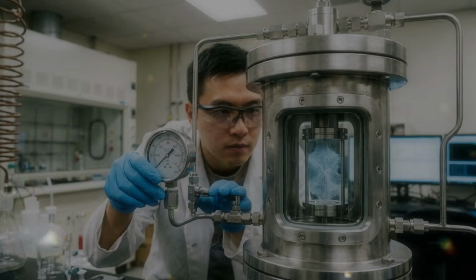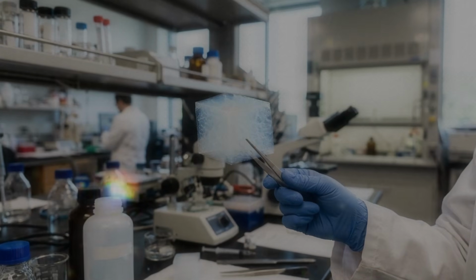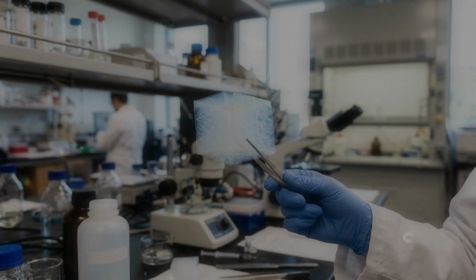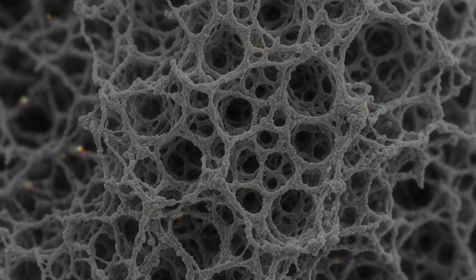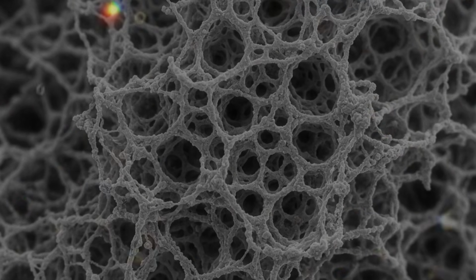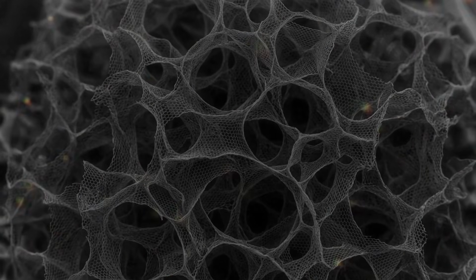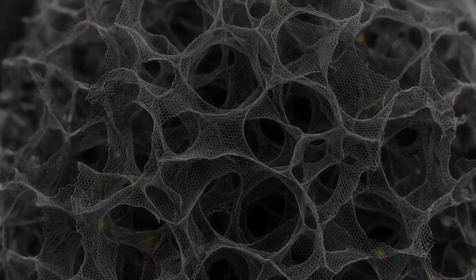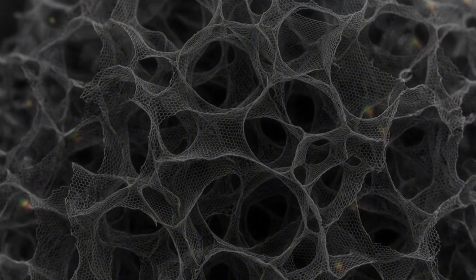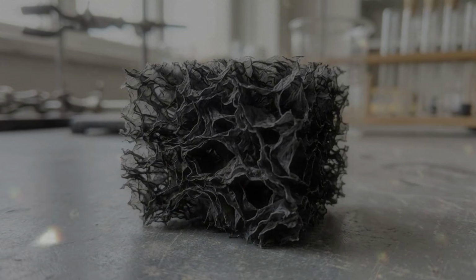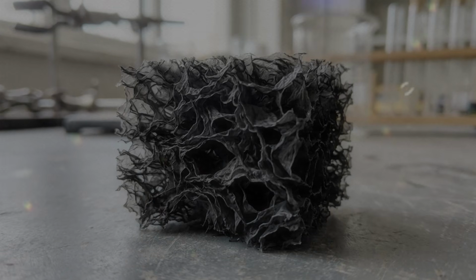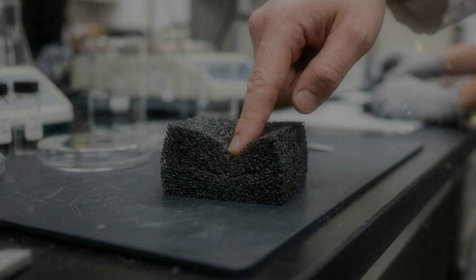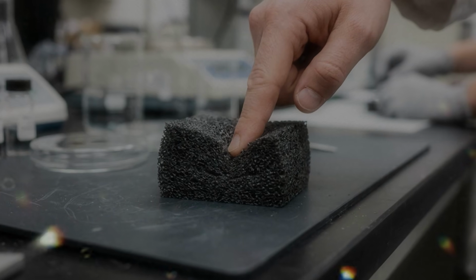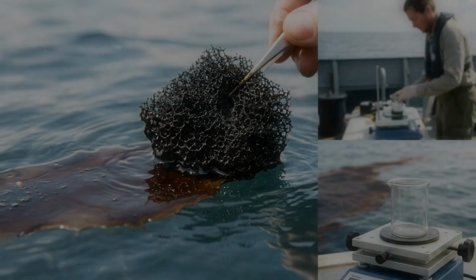This distinction does not make the material less impressive. A block large enough to see clearly can weigh only a few milligrams. A piece may be supported by the delicate centre of a flower without bending it noticeably. If placed beside a similar-sized piece of foam, charcoal, or plastic, the difference can be surprising. The low density begins with graphene, but the name Aerographene can create another misunderstanding. A single sheet of graphene is only one atom thick. It is not a foam, and it does not have a useful three-dimensional volume. It is more like an extremely thin carbon membrane.